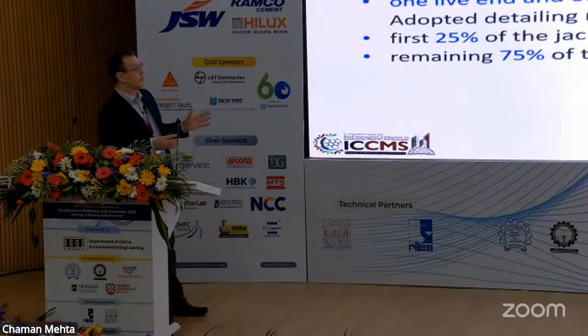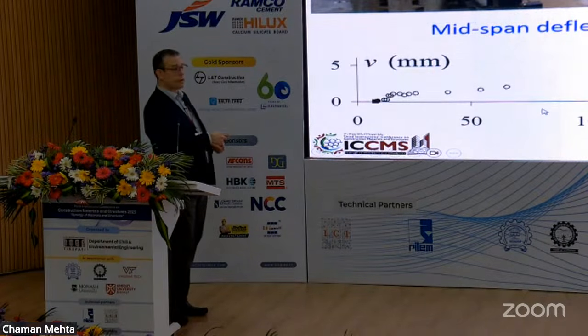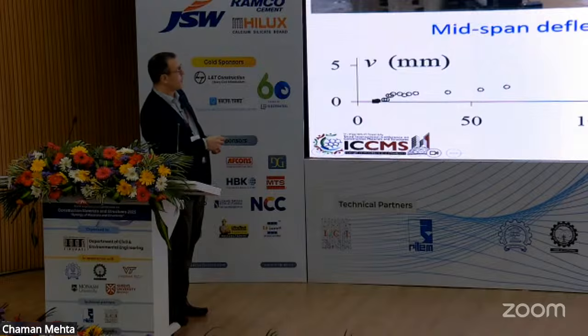So the interesting aspect, at least the trend, is to apply the pre-stressing 25% in the first day or first couple of days, and then the remaining 75% after a few days. Now, if I can ask you to look at these results here. Here you've got the 3 samples, simply supported. These are the results for the concrete one. The first one is exposed top and bottom.